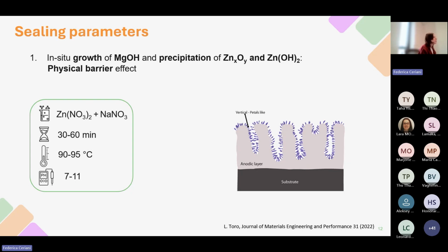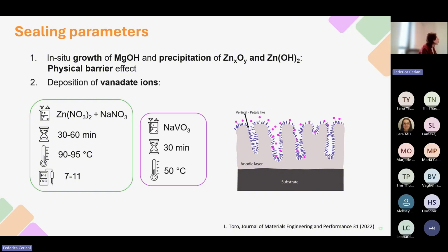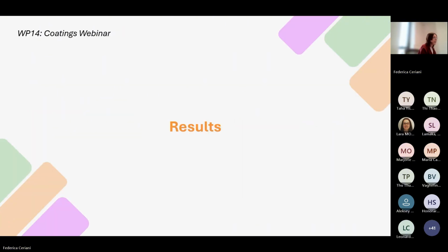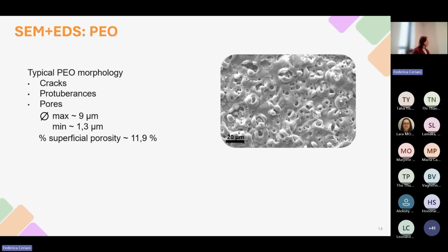In order to evaluate also the possibility of a chemical protective effect, a set of samples undergoes a second post-treatment phase, during which the samples are immersed for 30 minutes in a solution containing sodium metavanadate heated up to 50 Celsius degrees. During this second phase, the deposition of vanadate ions takes place, and vanadate ions are chemical corrosion inhibitors. Now we could start to comment on the results, starting from the characterization of the PEO-coated samples.